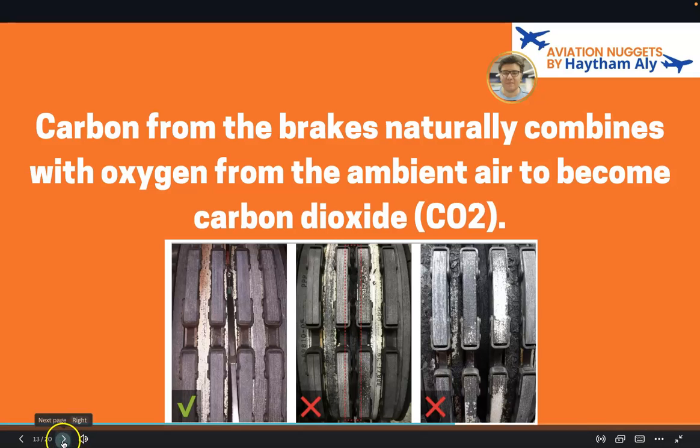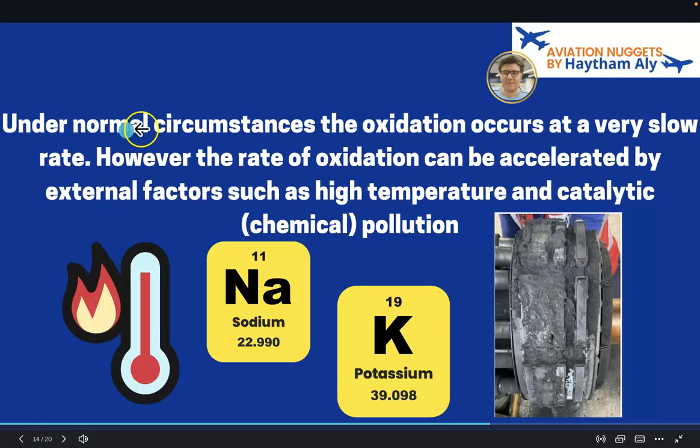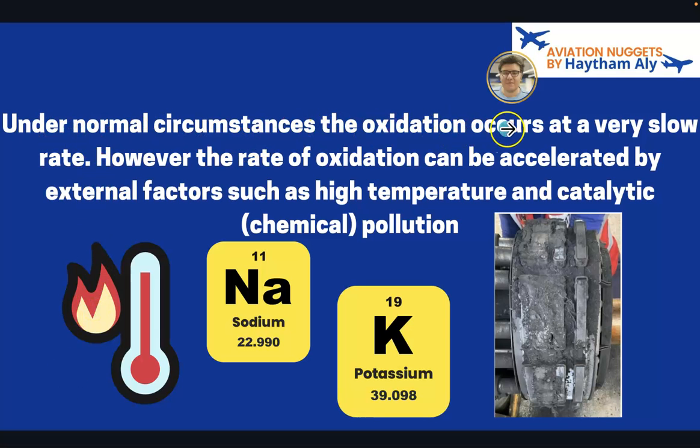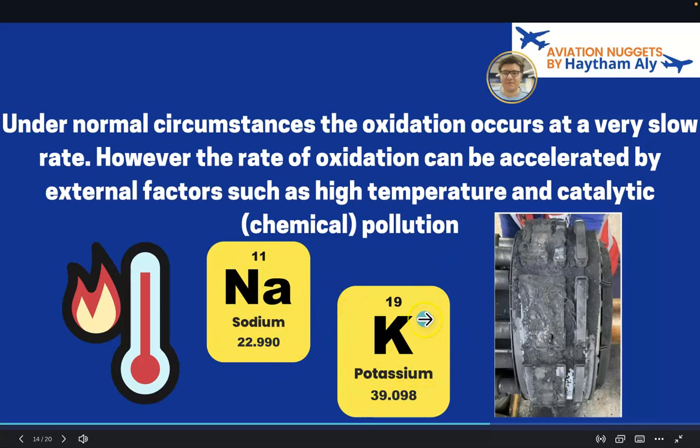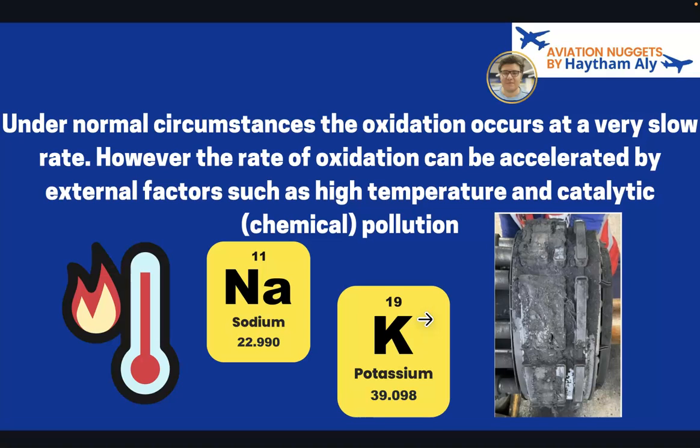Okay, everybody. So, under normal circumstances, oxidation occurs at a very slow rate. This is what I have just said. However, the rate of oxidation can be accelerated by external factors such as high temperature and catalytic chemical pollution due to sodium and potassium in the cleaning and de-icing fluid.